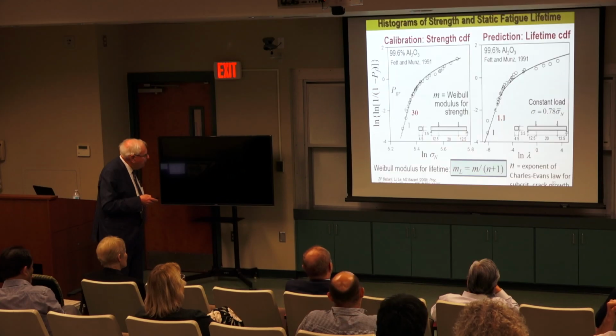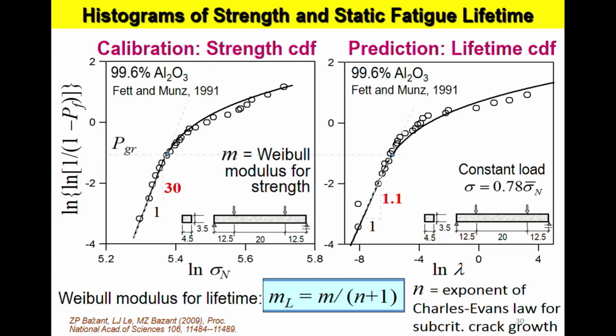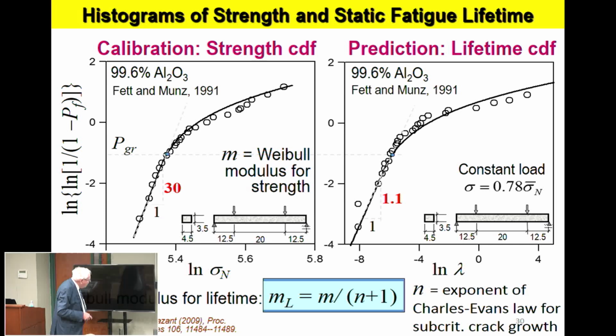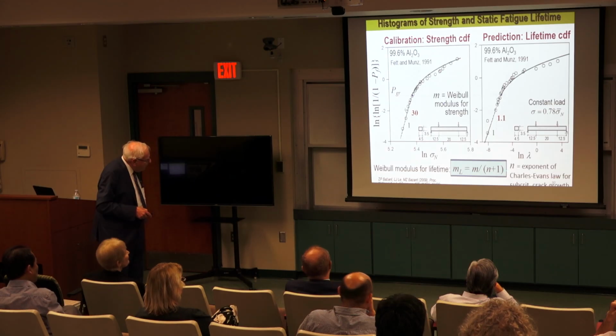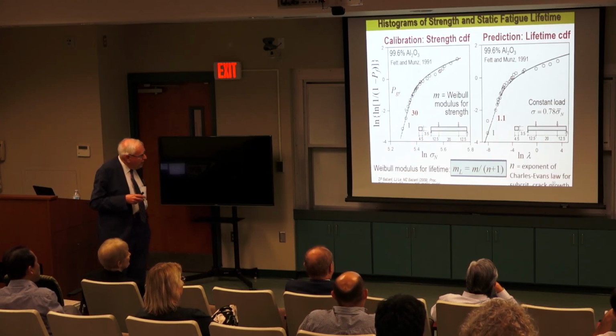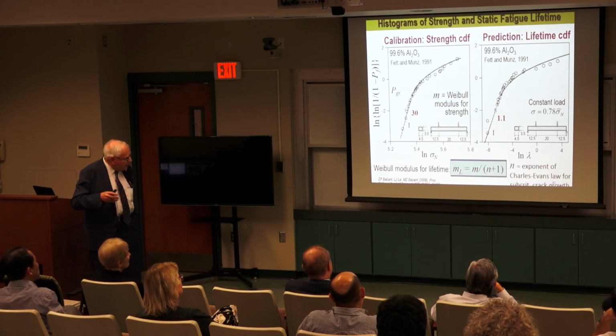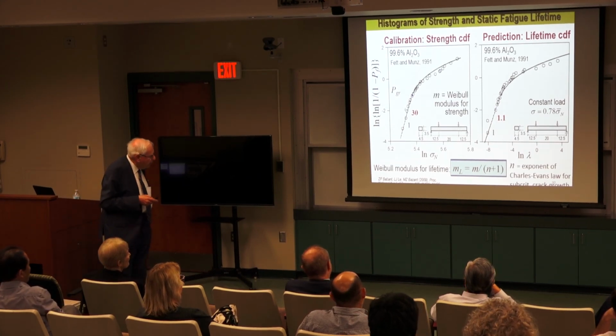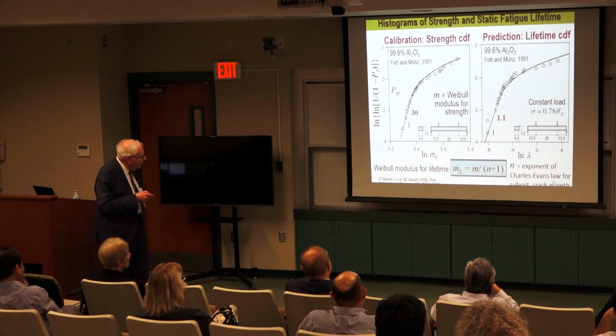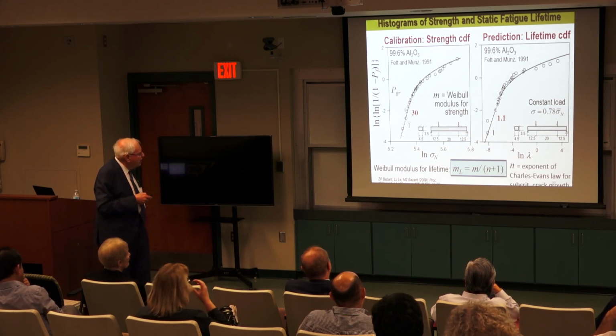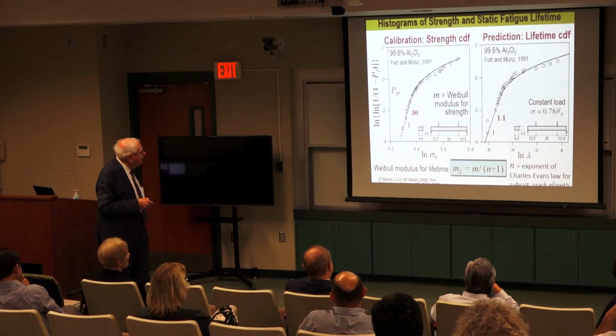In fact, it can be shown that the size effect of the Weibull exponent for lifetime, this is analytically derived, is the Weibull exponent for strength divided by n plus 1. N is the exponent of the subcritical growth law. So Charles Evans law, or in cycling it would be Paris law, which is of the order of 4 to 12, something like that. And this is one case where we can verify it.